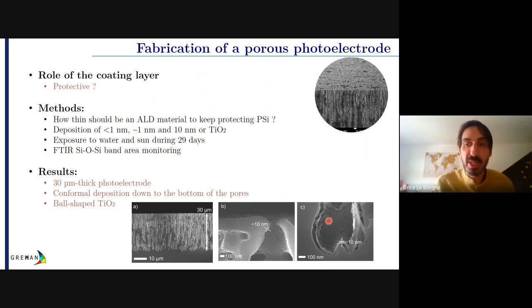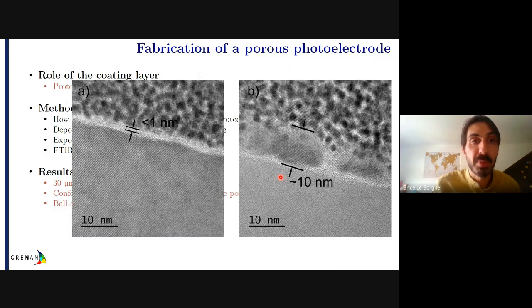So it's not really something we mastered initially. We could discuss later why it formed like this. But for the thicker layer, so the 10 nanometer, we had these balls that are very good for catalysis. This is a TEM of the other deposition, the thinnest one. So we can see it's less than 1 nanometer. It's non-ball shaped, but it's quite rough. You also see this roughness. So this was performed using only 5 ALD cycles. Okay. And these images are done on flat substrate. It's very complicated, we are still working on that, to image porous silicon.